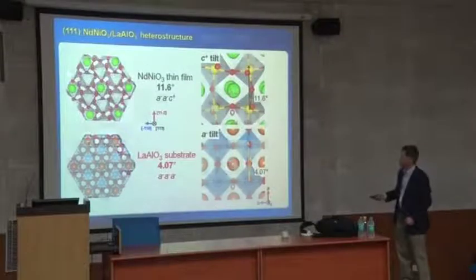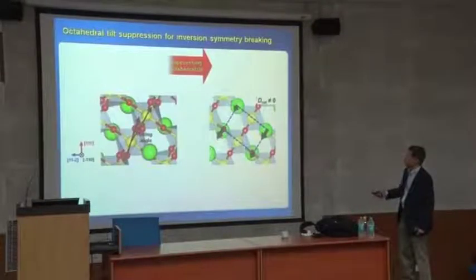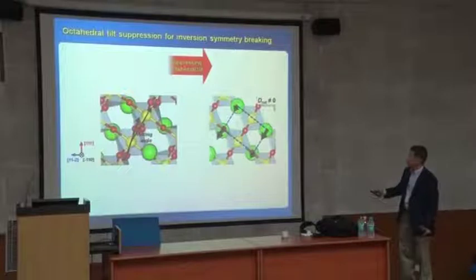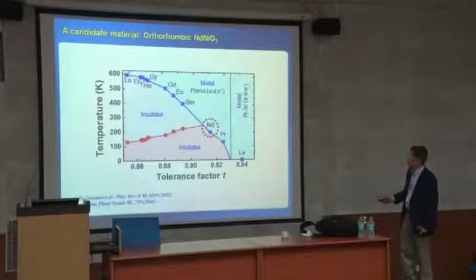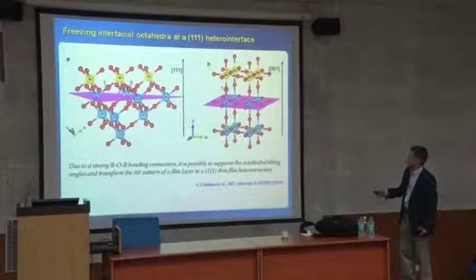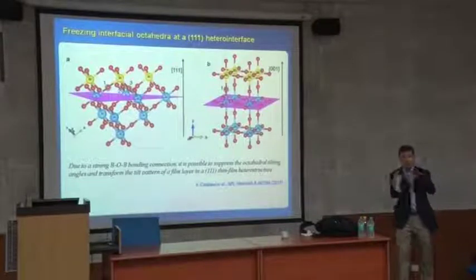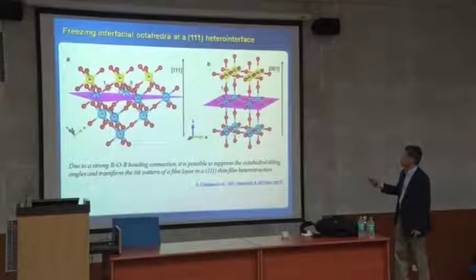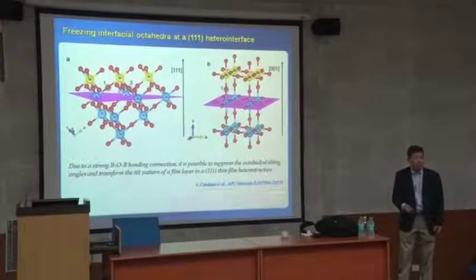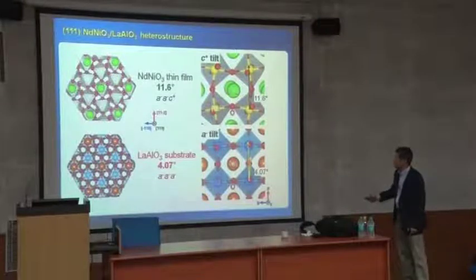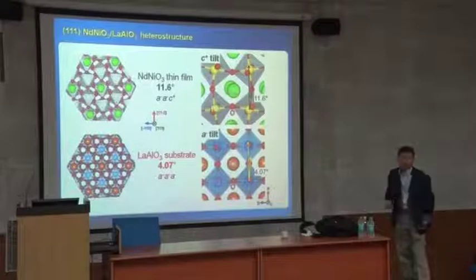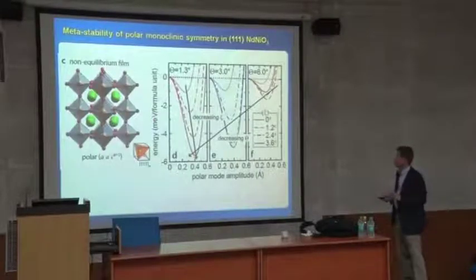Remember that? So your idea here is two things. One is this large tilting angle to low tilting angle, stretch it, make it polar, from antipolar to polar, one way. And then you use the 1-1-1 direction to make multiple bonding of octahedra rather than single bonding, using a different orientation of the infinite planes. So this will lengthen, eliminate substrate, and then 1-1-1 growth, and you make this one an ideal form of tilting from the polar to antipolar state.